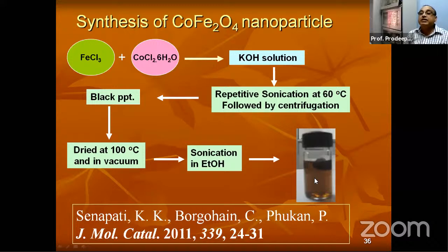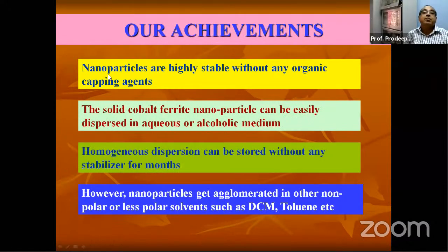Then what are the key features of our nanoparticles? For example, nanoparticles are highly stable without any organic capping agent. We have not used capping agents because most of the nanoparticles get agglomerated without capping agents, since the capping agent caps the surface of the nanoparticle so that it does not get agglomerated. But in our case, somehow it was stable without any capping agent. Solid cobalt ferrite nanoparticle can be easily dispersed in aqueous or alcoholic medium. Homogeneous dispersion can be stored without any stabilizer for months. However, nanoparticles get agglomerated in non-polar and less polar solvents like DCM, toluene, etc.